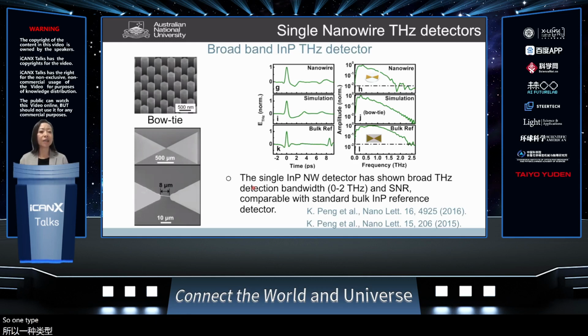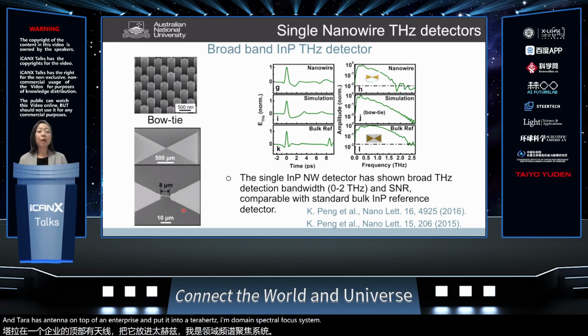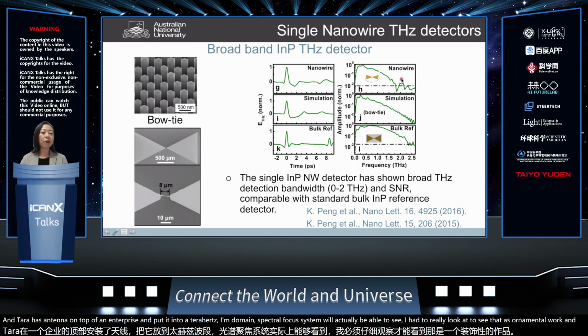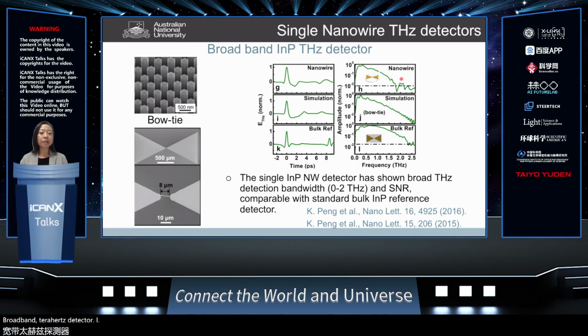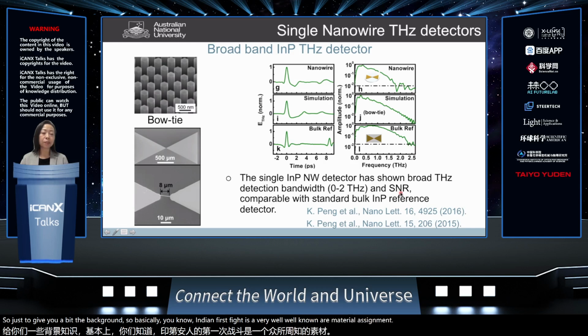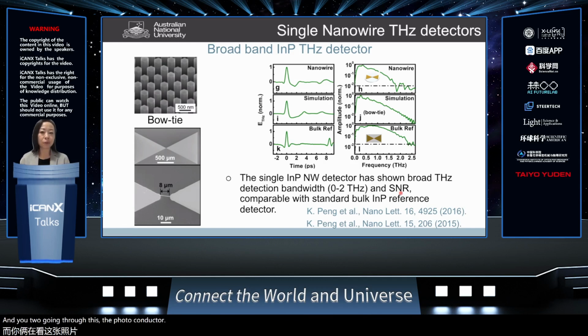So one type of device we're looking at is using a single nanowire as a terahertz detector. By using photolithography to make this bow tie type of terahertz antenna on top of the nanowires and putting it into a terahertz time domain spectroscopy system, we were able to see that our nanowire can work as a very nice broadband terahertz detector, which has a similar signal to noise ratio compared to the bulk indium phosphide reference detector. So just to give you a bit of background, indium phosphide is a very well-known semiconductor material that can be used as a terahertz detector through the photoconductive switch technique.